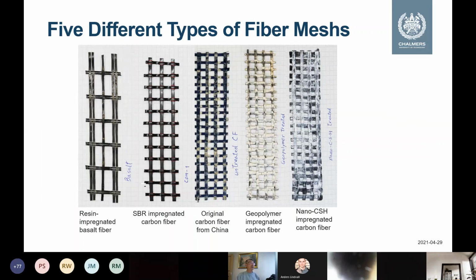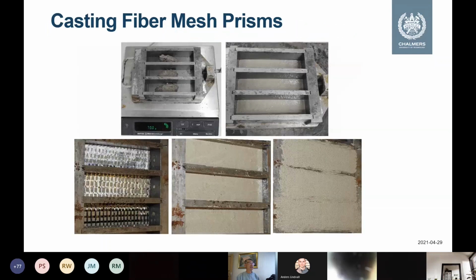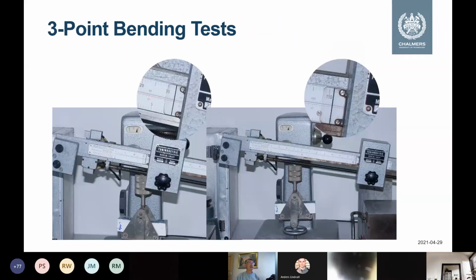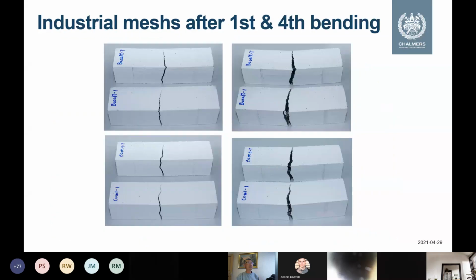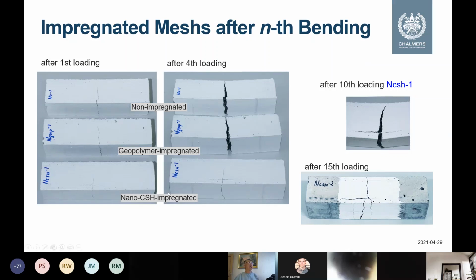Then we tested different industrial fibers in this project. This is the casting of the fiber, and then the testing. We used our old three-point bending test. For basalt fiber, it becomes broken after the fourth bending. This is a commercial rubber impregnated fiber, which also breaks after the fourth bending. Our non-impregnated carbon fiber breaks after the fourth, and the geopolymer impregnated one also breaks after the fourth.